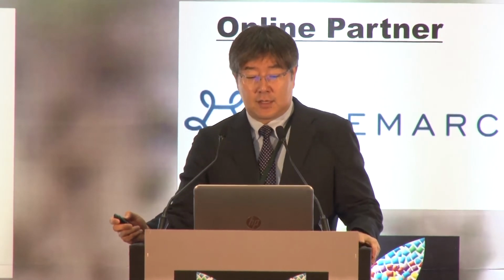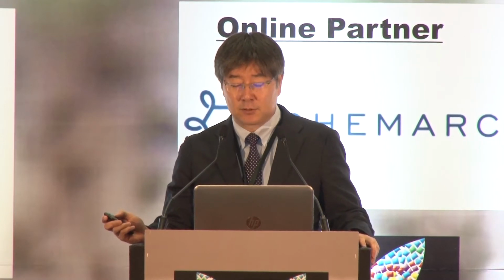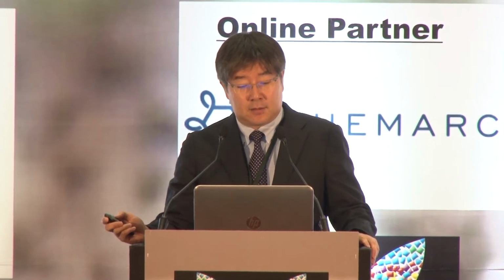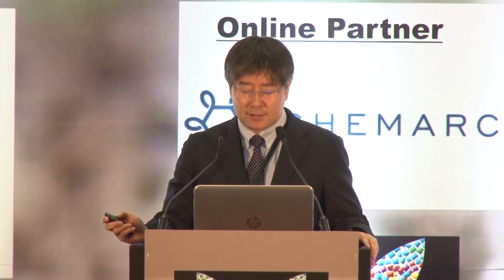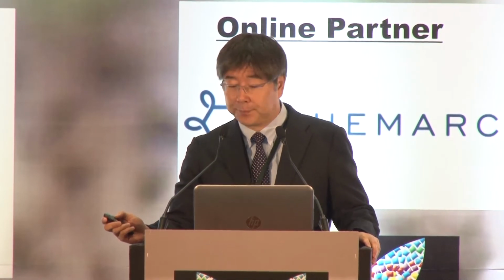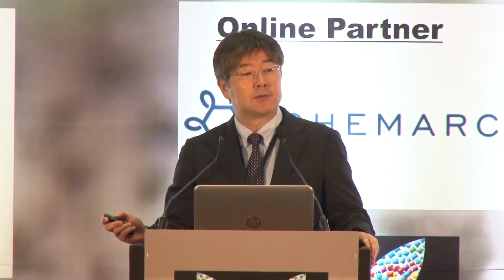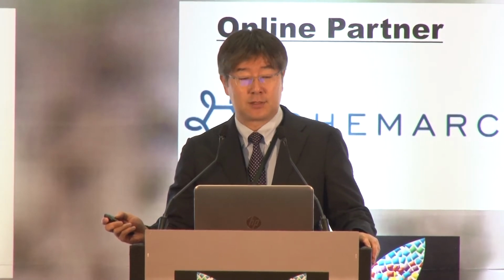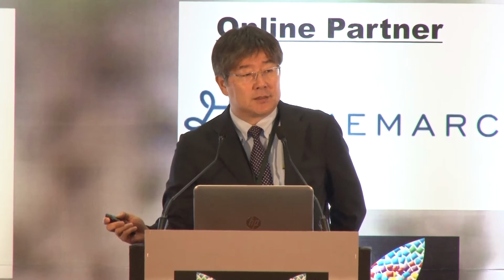And this is the weatherability of exterior parts in terms of surface gloss. The y-axis is gloss retained percent, and the x-axis is exposure time. Compared to the combination of reference 1 and reference 2, totally 0.2%, 0.1% LA1 can provide the same performance as the combination of reference 1 and reference 2.